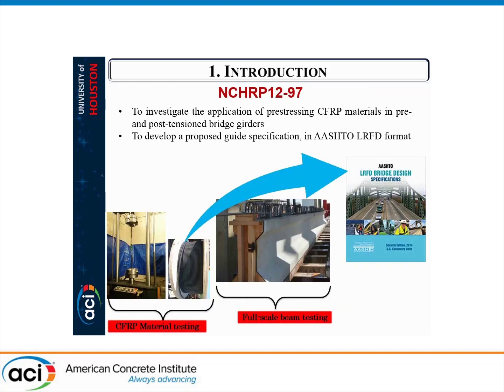So the CFRP project that we are working on has two main goals. First, to investigate the application of this material in bridge girders, both pre-tensioning and post-tensioning application. And more importantly, to develop design guidelines in AASHTO LRFD format. So we conducted several material tests to assess the short and long-term performance of this material. Then we implemented this CFRP material in design and fabrication of full-scale bridge girders with the slab, both pre-tensioning and post-tensioning, as I mentioned. And also we conducted flexural testing under monotonic and fatigue loading. And at the end, by collecting the data from other research studies and based on our results, we ended up with the proposed design guidelines to be included in the AASHTO.